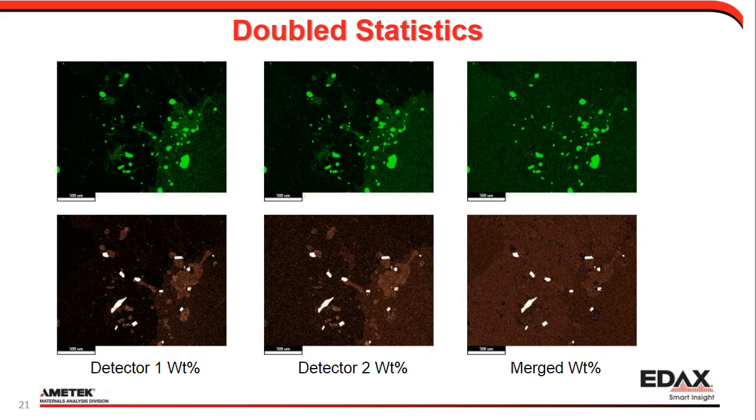The same thing for the zircon map we have down the bottom. We can see there is a slight contribution from the silicon, but not too much. We have more of a contribution from the iron inclusions. And when we then add the two together, add the spectra together, not the maps, the spectra, and do math on it, we can get rid of most of that iron, the strong iron inclusion and the silicon contribution.